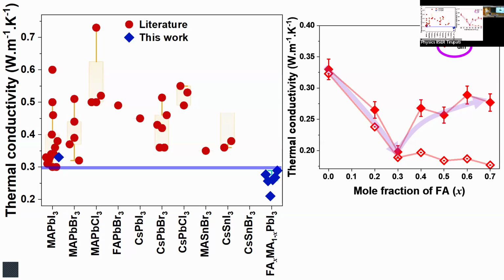FA has a dipole moment. FA is rotating as much, but FA has a dipole moment which is 1/10 of MA. And it is the dipole moment on MA that scatters the phonon, allows it to interact so well with the ionic lattice that is vibrating. When the dipole moment is low, though it's rotating, the low dipole doesn't scatter the phonon so efficiently. So FA is scattering less, and that's why it's coming up.